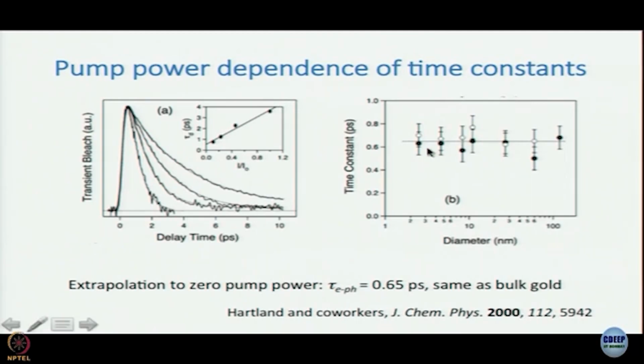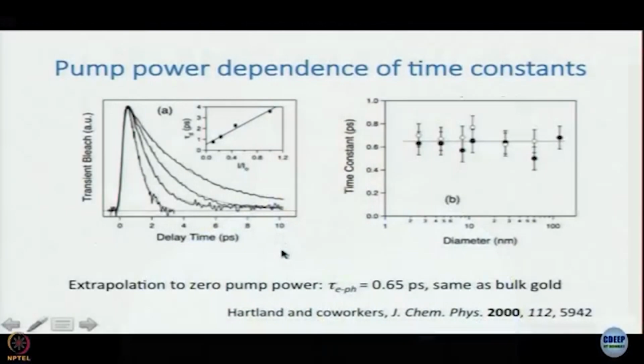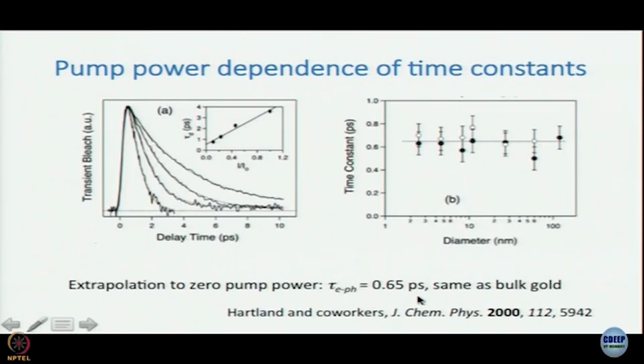Now, what they showed is that first of all, if you look at this time constant, how do you know what the time constant is? So, what they did is in this graph in the inset, they extrapolated it to 0 pump power. So, this is sort of like the infinite dilution we must have read, right. Actually, you cannot achieve infinite dilution, but you always extrapolate and find out what it is. So, by extrapolation they found that at notionally 0 pump power, the electron phonon coupling time constant is equal to 0.65 picosecond, which interestingly is exactly the same as what is there for bulk gold.